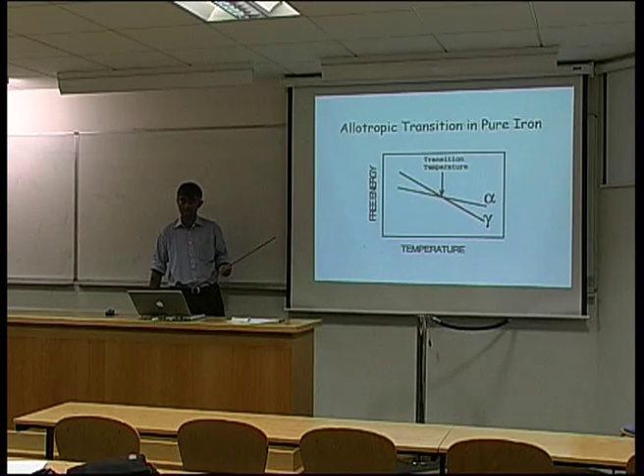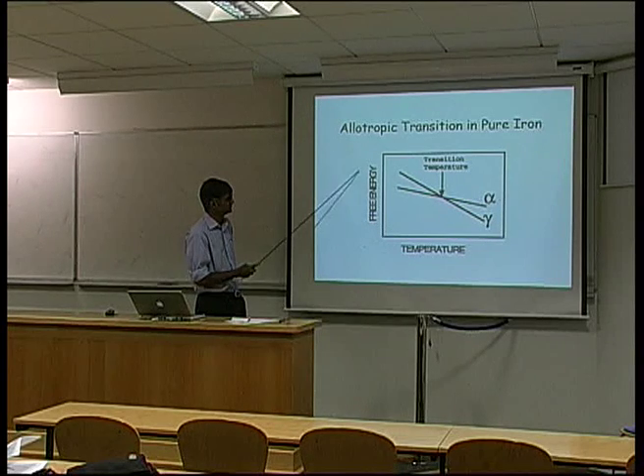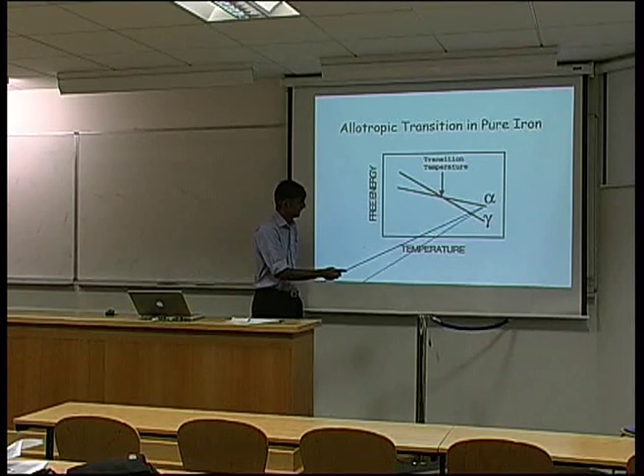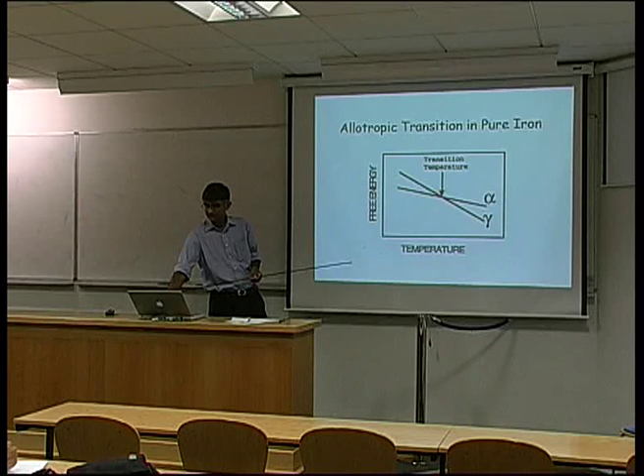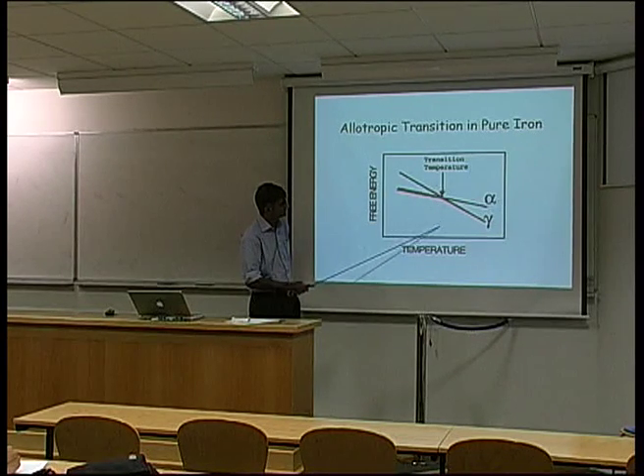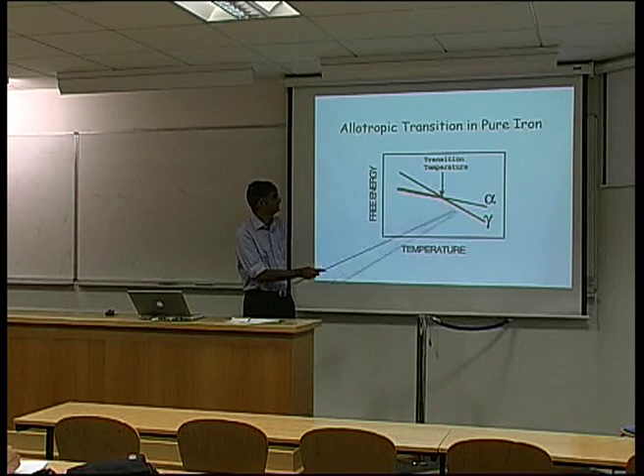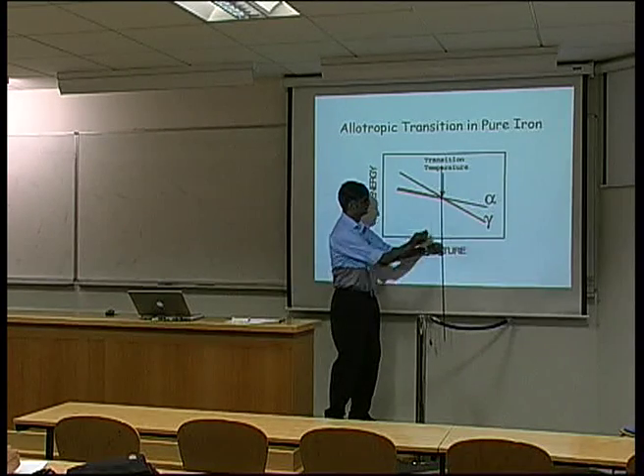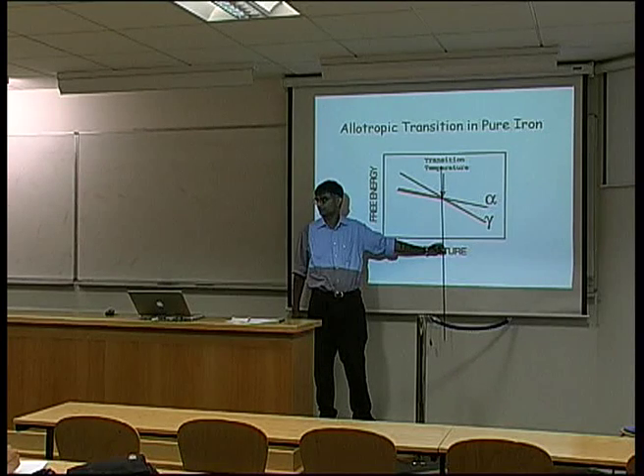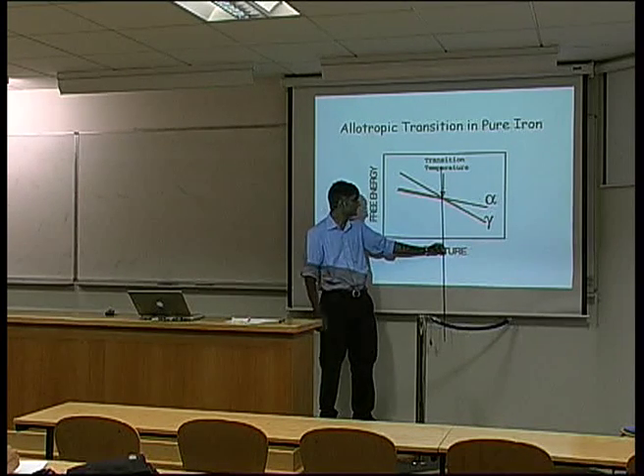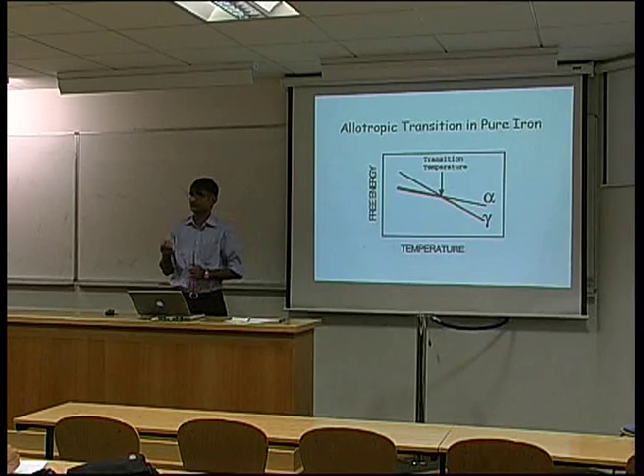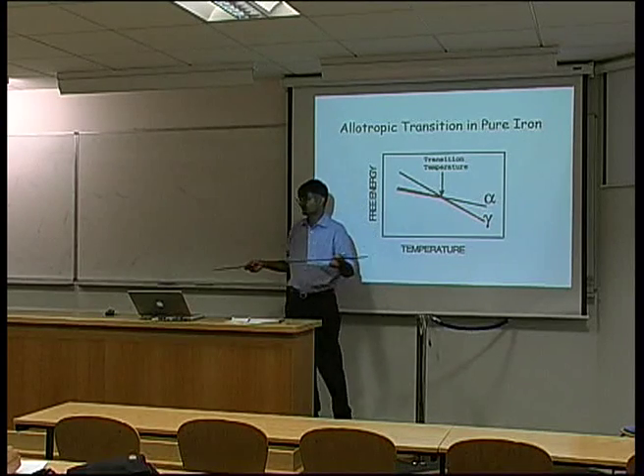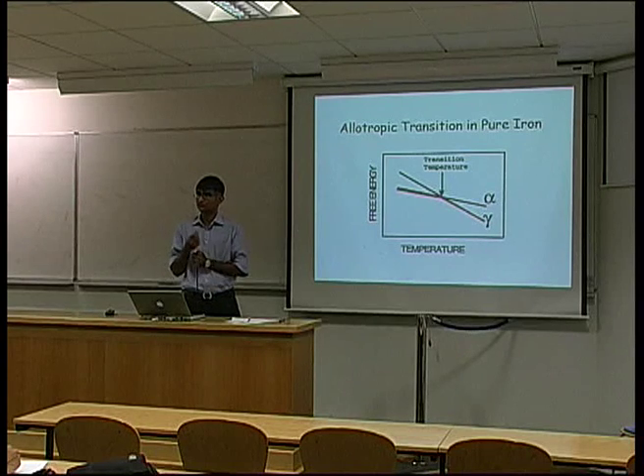In the last lecture, we plotted the free energy of pure iron in its cubic-F crystal structure and pure iron in its cubic-I crystal structure. This is the temperature at which the two phases are in equilibrium. The red line here represents the condition of minimum free energy. So if I plotted a phase diagram on this side, I would only have gamma existing because it's the lowest free energy phase, and on this side I would only have alpha. But again, this is a pure substance — I don't have any axis here which defines composition. And today's main task is to deal with solutions.